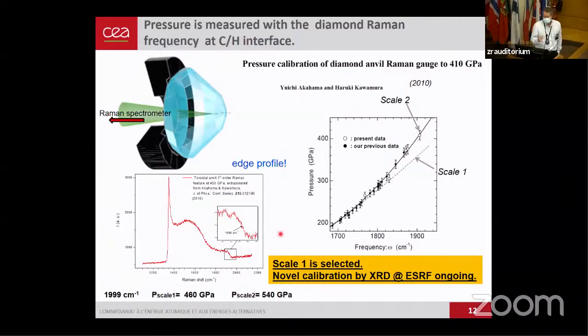Then the other important question is, how do we measure the pressure? And in this pressure range, there is no calibration. We are not in front of a synchrotron where you can use a metal to measure the pressure. The luminescence gauge like Ruby, which is the standard measurement of pressure in this 1 million atmosphere range, is not valid anymore.